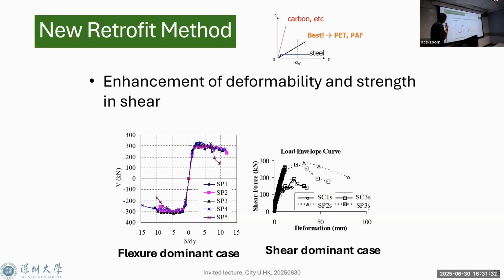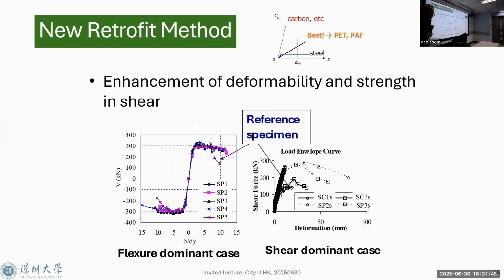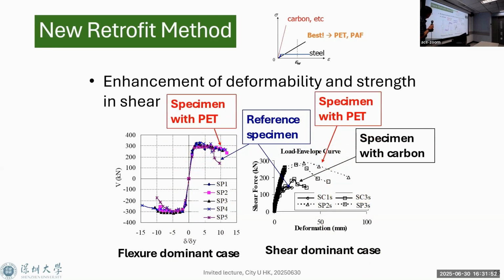Then once we use the deformable material, which is PET fiber, this PET material, we can have better seismic performance like this. So the specimen with a PET fiber has better seismic performance than the carbon reference specimen.